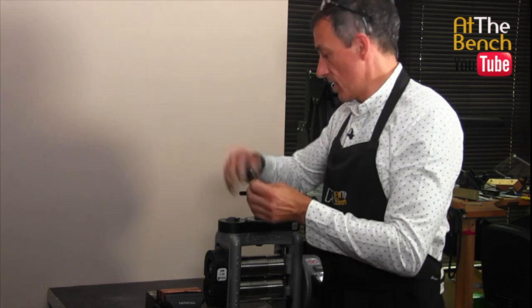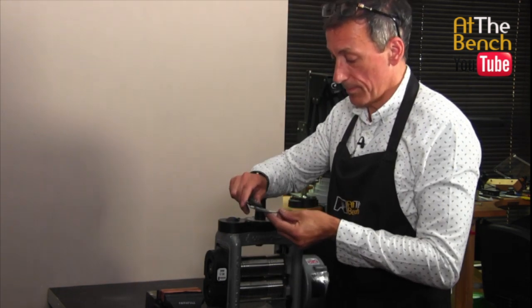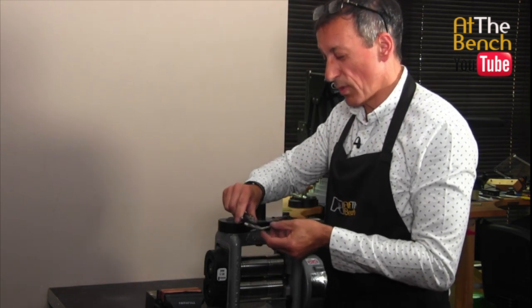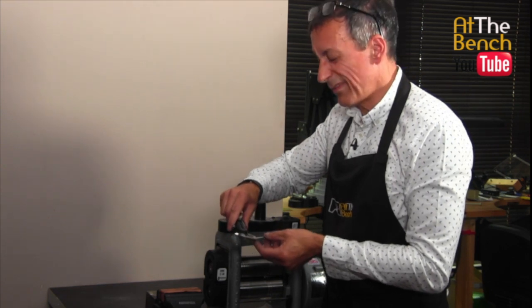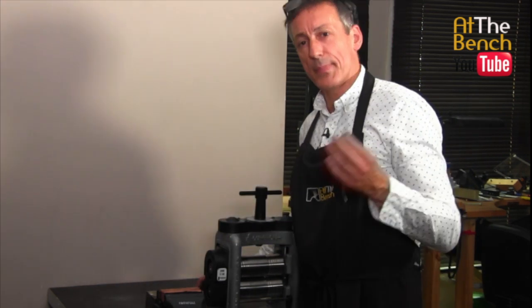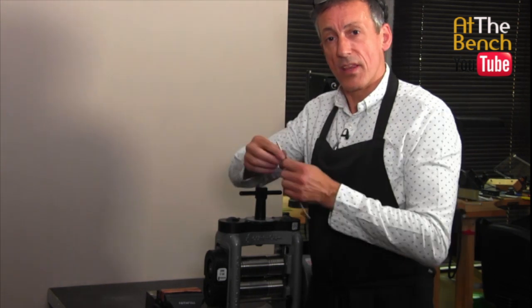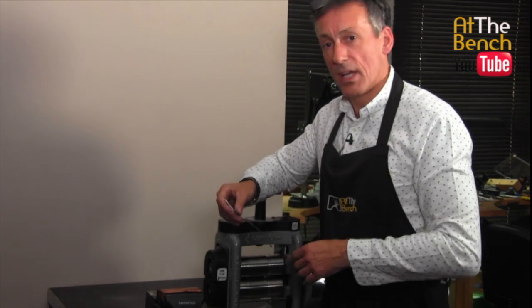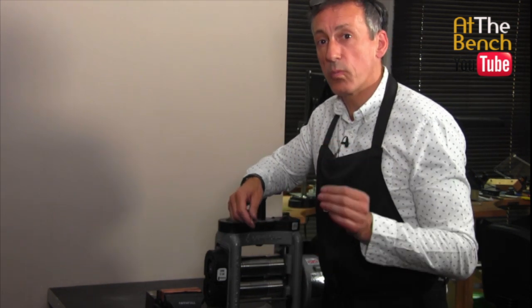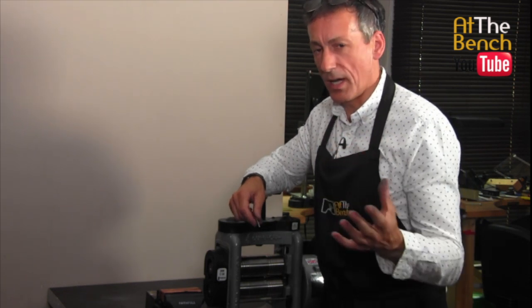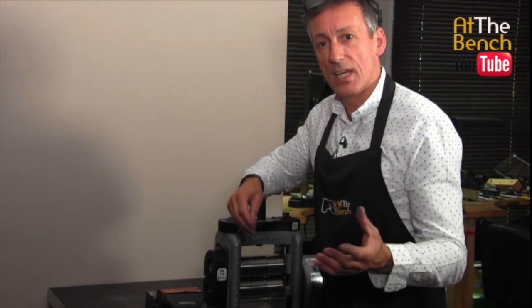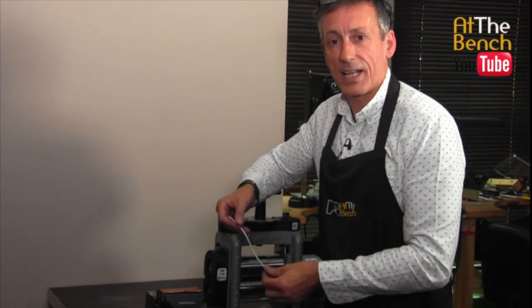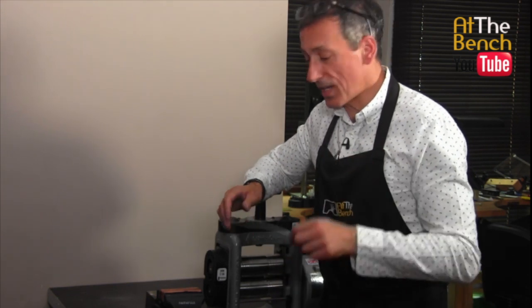We reduced the thickness by, it was 3.2, it's down to 2.2, so we've reduced the thickness by about 1mm, and it spread that 0.5mm. So always start off with a piece of wire about 0.5mm narrower than what you need for the final ring to be exactly the right width. So there we go, D-section wire.